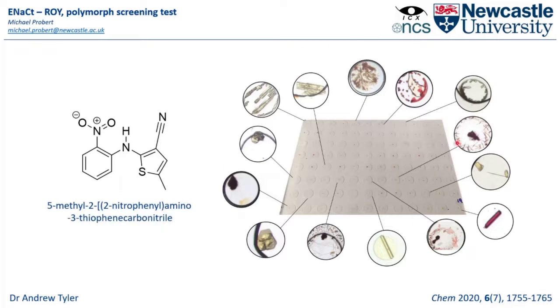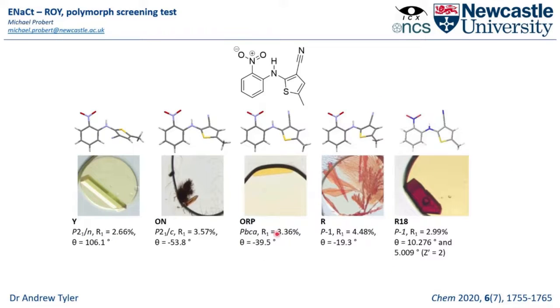And all of these can be found within different conditions. Some grow concomitantly within the same well, so we get different polymorphs within the same conditions. That's to be expected. The energy differences between these polymorphs is quite small. But if we do this analysis and we go through and we look at all of the structures that we get, we actually access all of the known forms at the time of publication, anyway, all of the known forms from the solution phase, this yellow, orange needle, orange-red plate, the red crystal, and we found another polymorph of this R18 sample. We'll circle back to this R18 in just a couple of slides. But this shows immediately that we can do polymorph exploration relatively quickly with relatively small amounts of material.